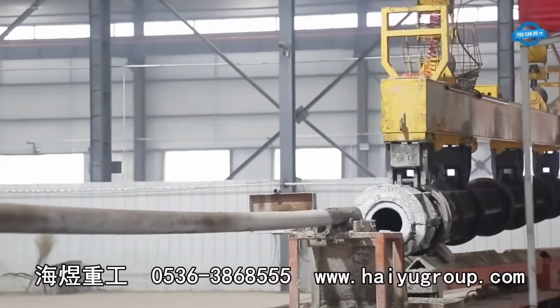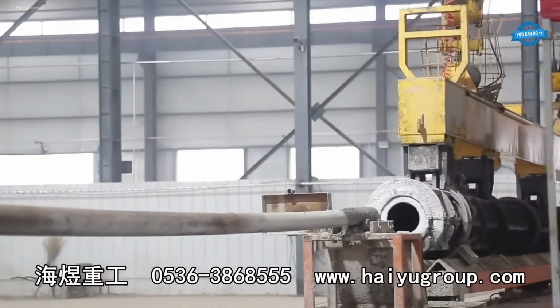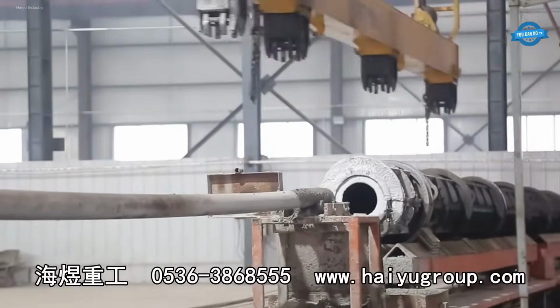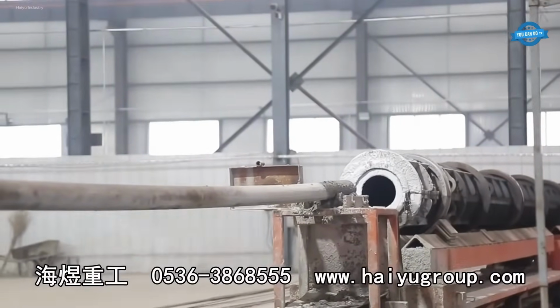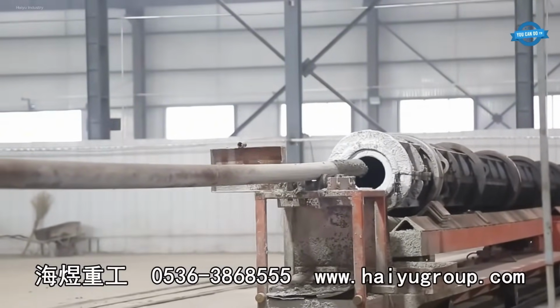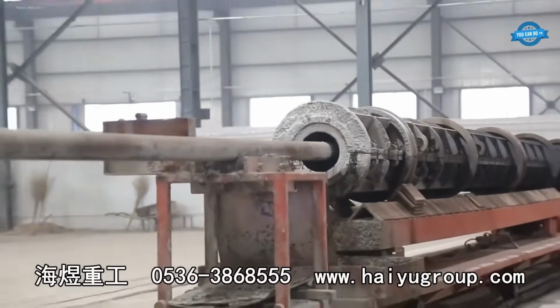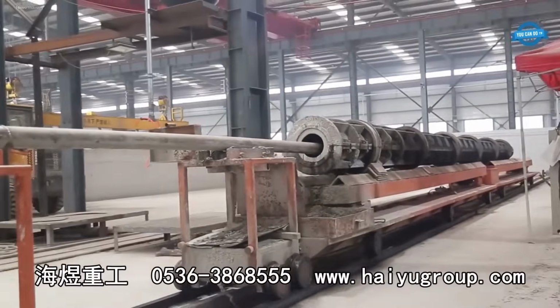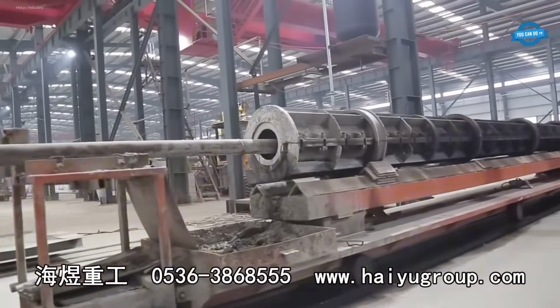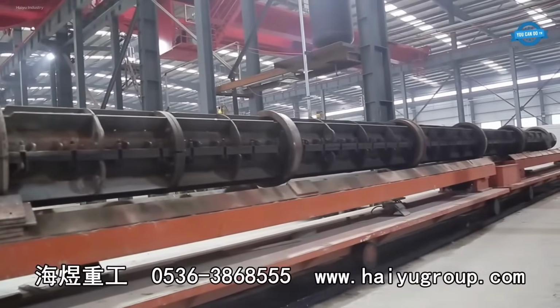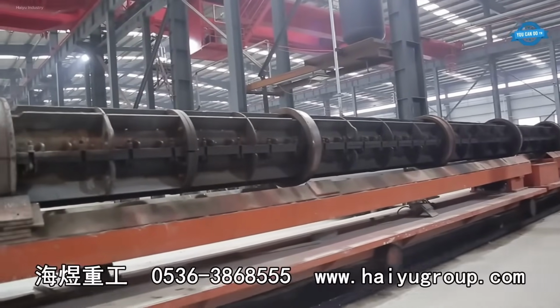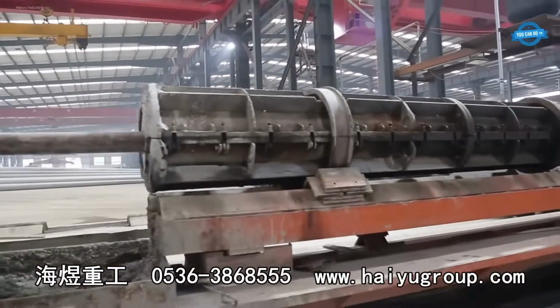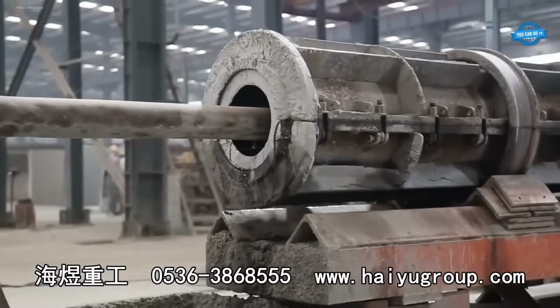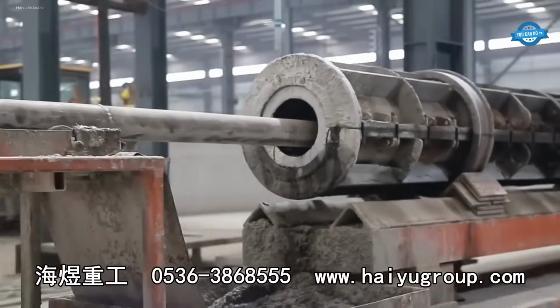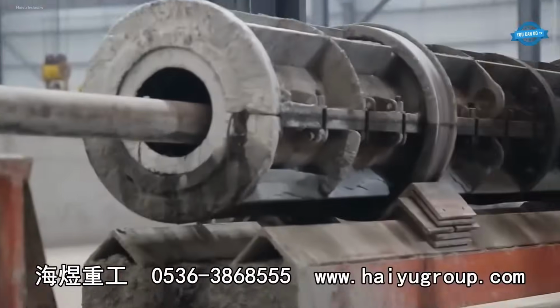The closed mold is then clamped securely and transferred to the centrifugal spinning station. This spinning machine accelerates the mold to high rotational speeds, typically 700 to 1000 RPM. The centrifugal force compacts the concrete against the mold walls, eliminates voids, and forms a dense, high-strength outer shell around the steel cage. Excess water and air are expelled during spinning, enhancing the concrete's final strength.